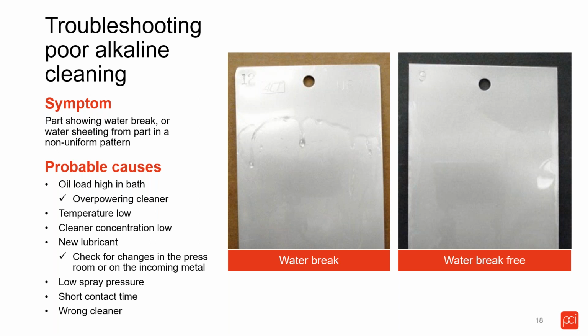Sometimes you might be running more square footage and end up with a shorter contact time than you initially planned due to increasing line speed. So if you drop from 90 seconds to 60 seconds, you might see a performance change in your cleaner due to that. And then there's low spray pressure based on routine maintenance, making sure your nozzles are clean. If you can't get the chemistry to the part, how are you going to get it clean?